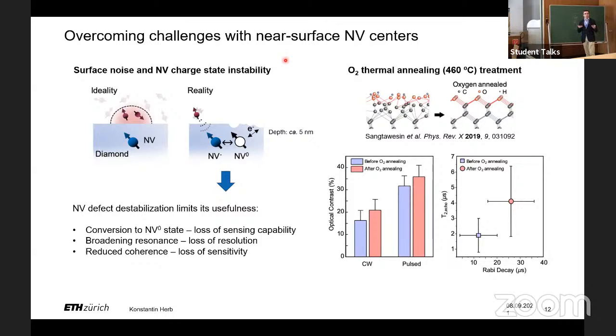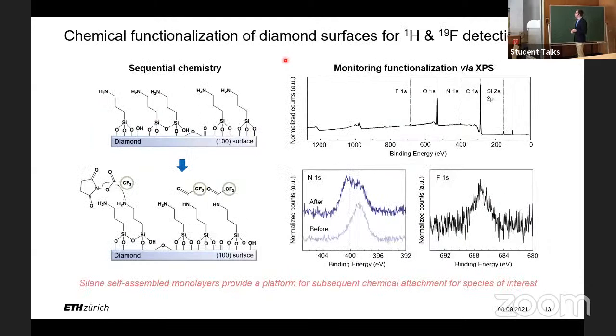How can we now actually bring molecules to the surface? Well, we chemically modify this oxygen-terminated surface by direct silanization. For the results I'm sharing today, we actually attached amine-labeled silanes to show the general stability of that approach, because like that, you can in the end attach any molecule you want with hydroxysuccinimide ester-labeled target molecules. And here in this case, we just attached a terminal CF3 group.